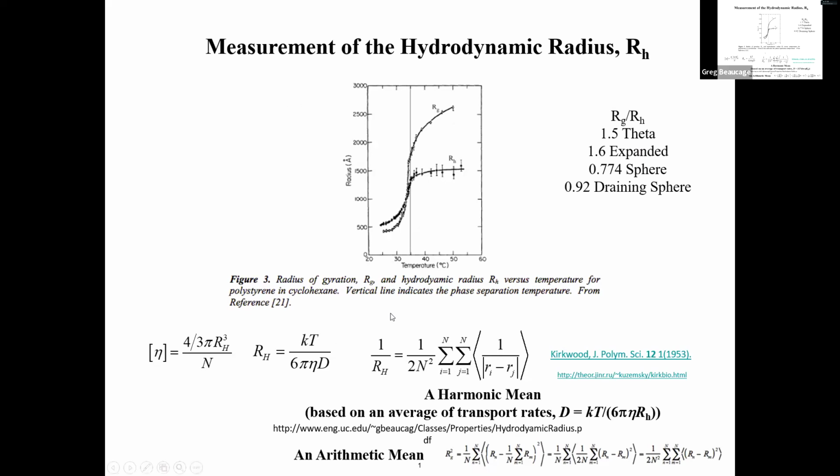And if the chain's like there and none of the solvent is stuck, then it moves around kind of freely as a worm, then that's the Rouse limit of it. So there's a Zimm limit and a Rouse limit to how a polymer in solution acts. Right. The Zimm limit's kind of the simple thing, it's a sphere.